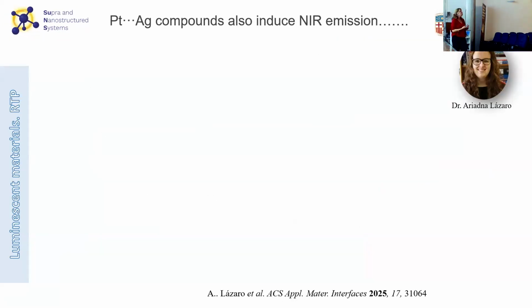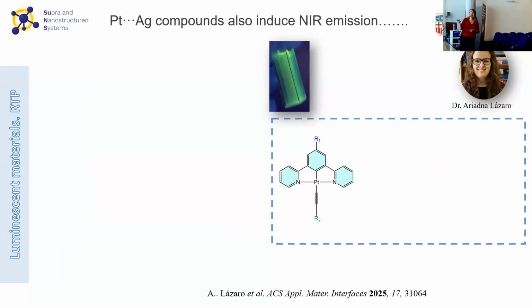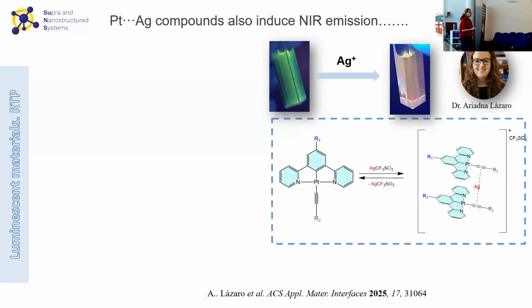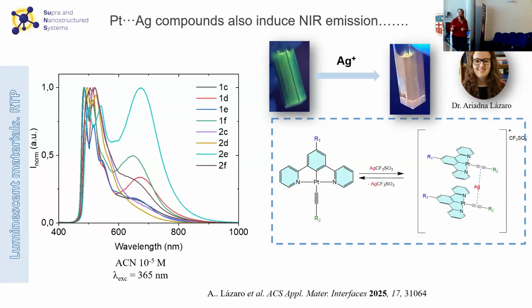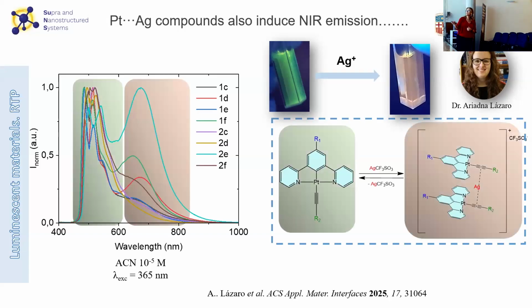But we can also induce tuning of the luminescence, not only by playing with solvents. We can also induce proximity between the individual molecules by making some heterometallic compounds. In this case, what Ariadna made is putting in contact a solution of this platinum compound with a silver salt, and we can directly observe by naked eye a change of the color from this yellow-green emission to this orange color. This is due to the formation of this heterometallic system, making the platinum centers closer to each other. This was also observed in the corresponding emission spectra, with the presence of this new band at longer wavelengths for the heterometallic systems.